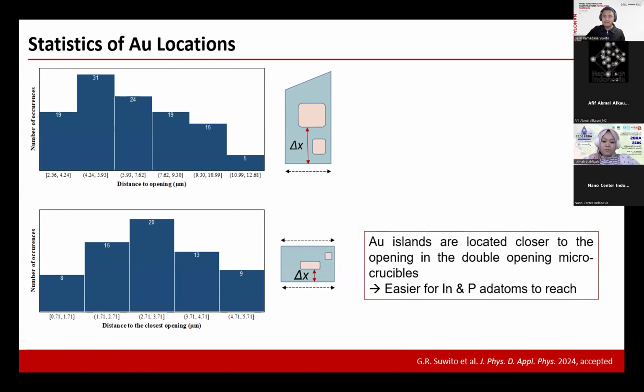And interestingly, when we used a double opening microcrucible, which is schematically shown in here, where you have two openings instead of one, you see that the distance to the openings of this main gold island becomes twice shorter. So this makes the double opening microcrucible potentially usable in the CBE lateral epitaxy process, because it will make it easier for the indium and phosphine adatoms to diffuse into the gold, because the distance is now twice shorter.